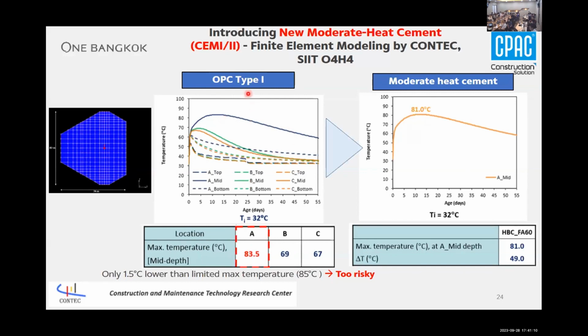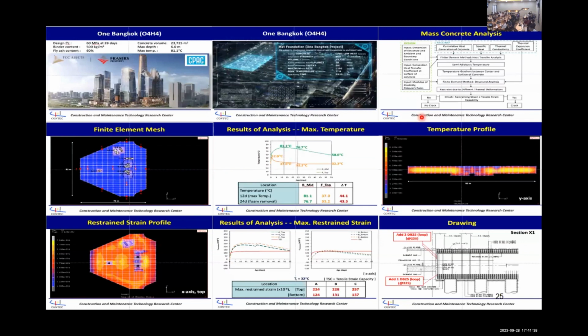So we changed our mind to change the cement type. Rather than only using fly ash at 60%, we use moderate heat cement combined with the fly ash at 60% as well. After that, we calculated the model again. We get the peak temperature around 81 degrees Celsius. This is something the owner became happier about, because the number is reduced. And after that, we ran the preliminary model. And this one, SIT and the team analyzed in detail the structure, and they get the peak temperature around 81, something like that, as I mentioned.